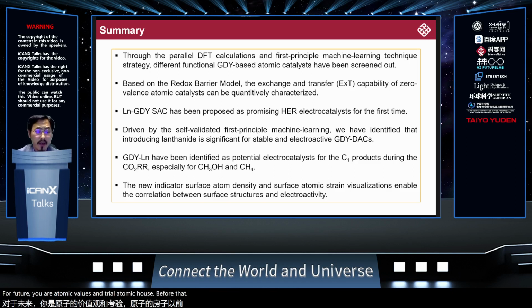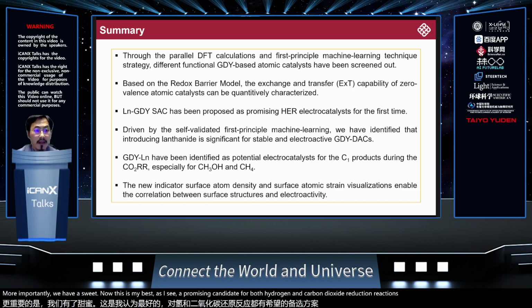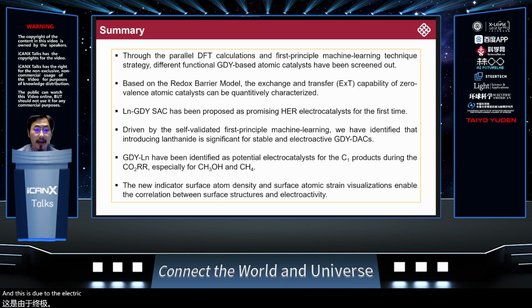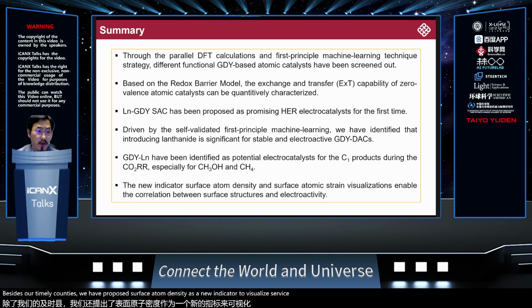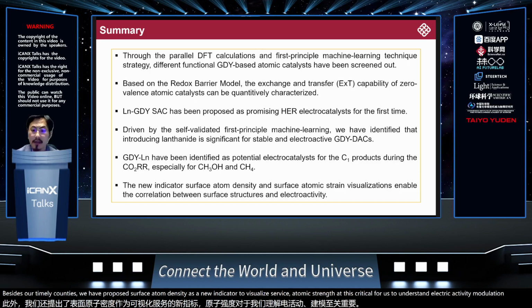We further considered that the introduction of the lanthanide is significant for high electroactivity and stability. More importantly, we have screened out lanthanide-based SAC as a promising candidate for both hydrogen evolution and carbon dioxide reduction reactions. And this is due to the electronic optimization by the orbital coupling effect of the f bands. Besides atomic catalysts, we have proposed surface atom density as a new indicator to visualize surface atomic strain. And this is critical for us to understand electroactivity modulation in nanoparticles.